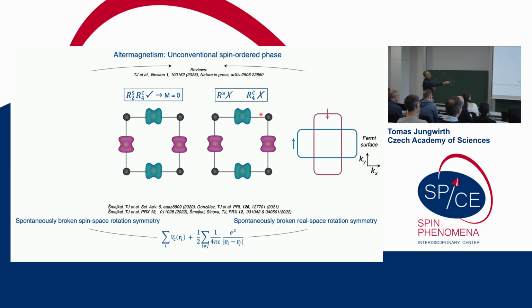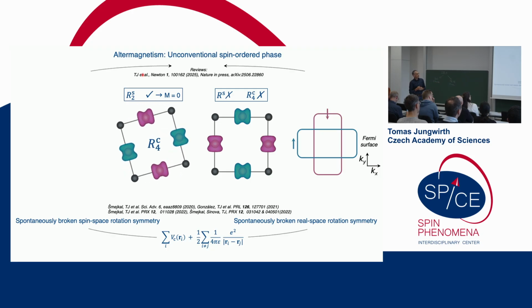And that's a symmetry which combines the spin space rotation with the real space rotation transformations. So what do we mean by this is that let's say I start with this state, and let me first apply the fourfold real space rotation on this state, and this is what happens. So I just rotate the lattice by 90 degrees, and what you see, I end up in a different state here. And yes, the fourfold real space rotation symmetry is broken.